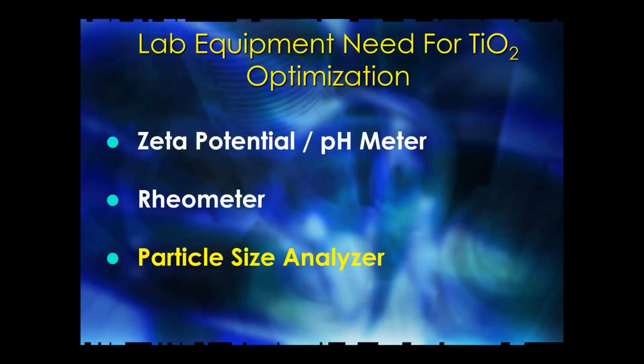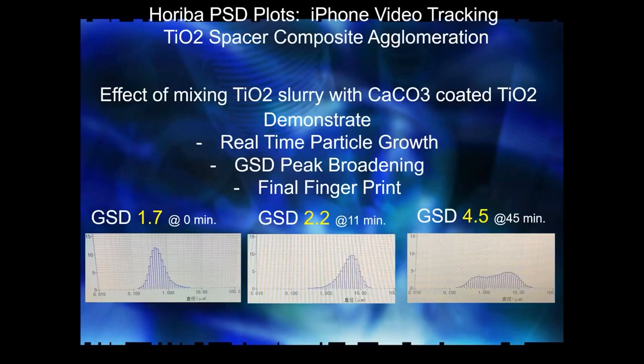I'm going to skip over rheometers and go to particle size analyzers. We can take the Horiba 950, and I can take my iPhone and do a video tracking of the particle size growth. And this was an experiment we were doing to make a composite. So we did a blend. The titanium dioxide was coated with calcium carbonate, which was acting as a spacer, but you can only put a certain amount of it, up to maybe 15%, to displace the TiO2. And what we were trying to do is make a composite, and we wanted to follow the particle size of the composite. So what is GSD?